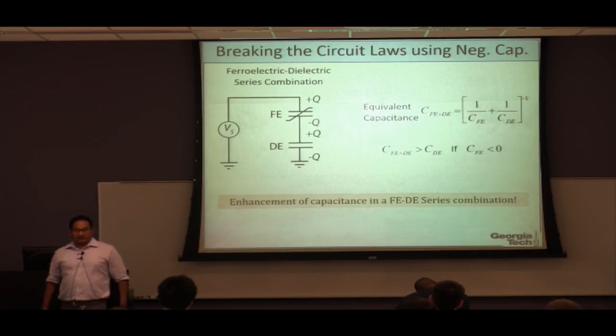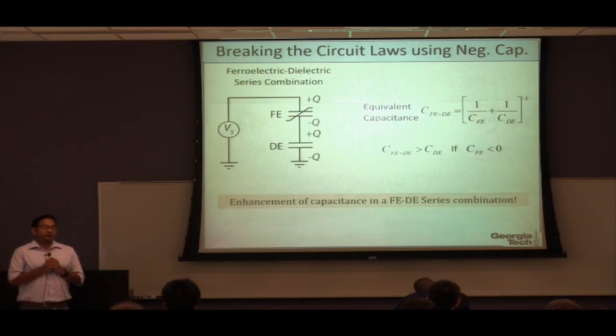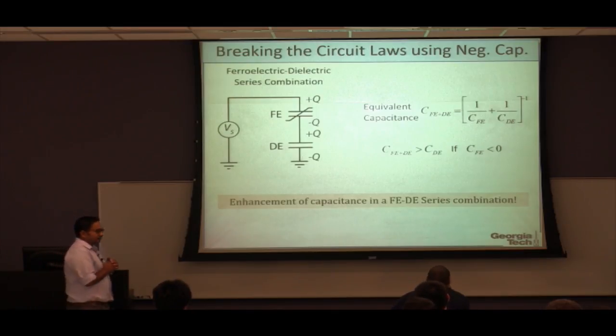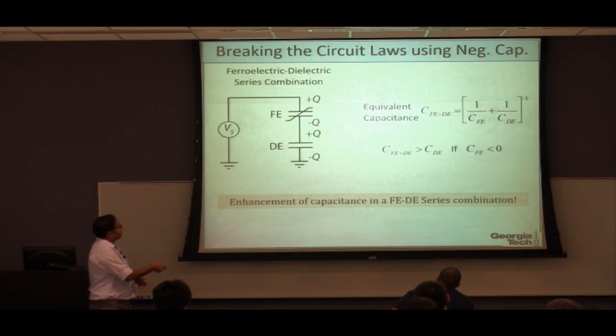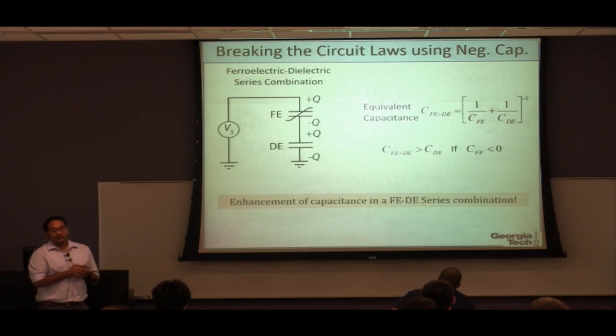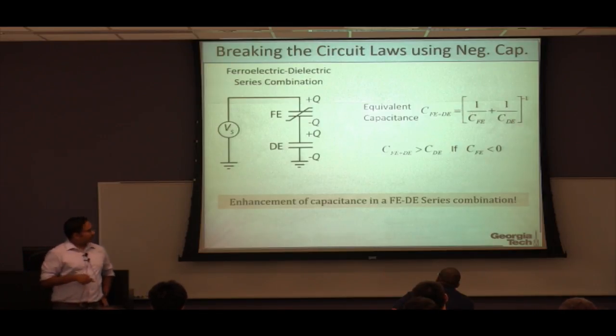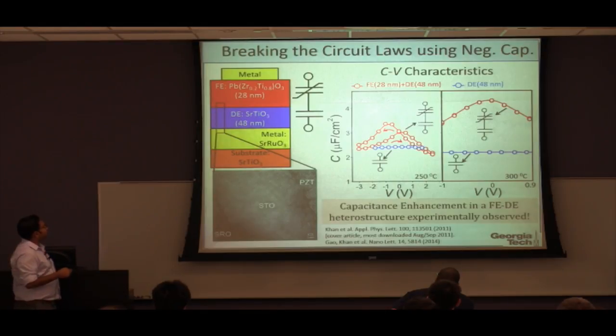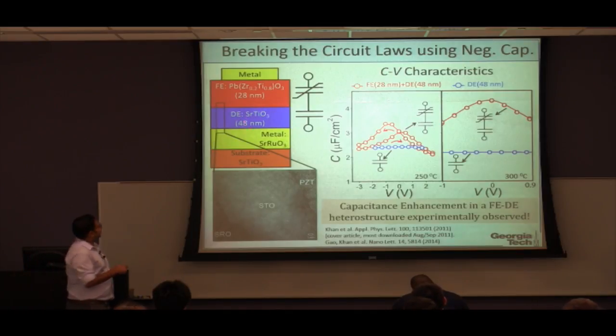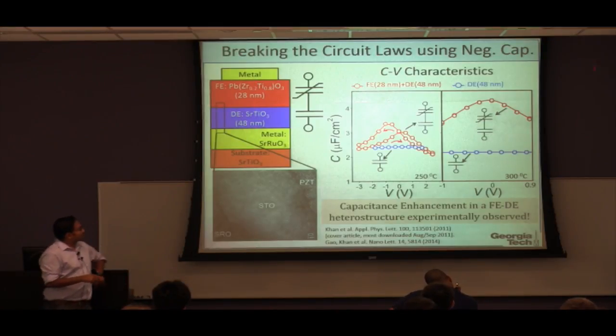But now take a case where you have a negative 2 picofarads and 1 picofarad. And if you do the simple law, you will see that the total capacitance will come out to be 2 picofarads, which is larger than the 1 picofarad. And essentially, this is the experiment that we set out to do. The next experiment was that we took a ferroelectric material and another dielectric material and put them in series in this kind of a heterostructure here. And these are the experimental results.